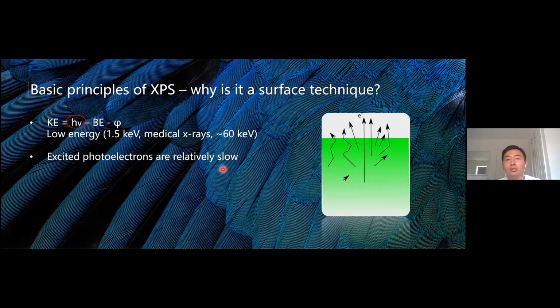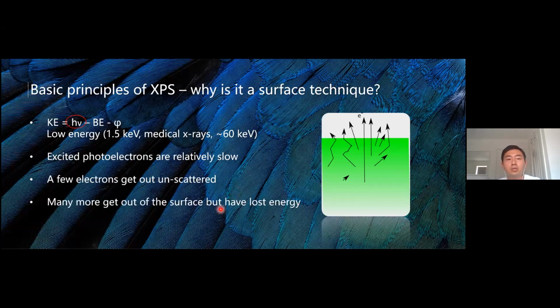Therefore, during travel, most of them will hit other atoms in the sample and lose energy. So only a few electrons can get out unscattered, which gives us the photoelectron peaks in the spectrum. And many more get out of the surface but have lost energy, which make up the scattered background.